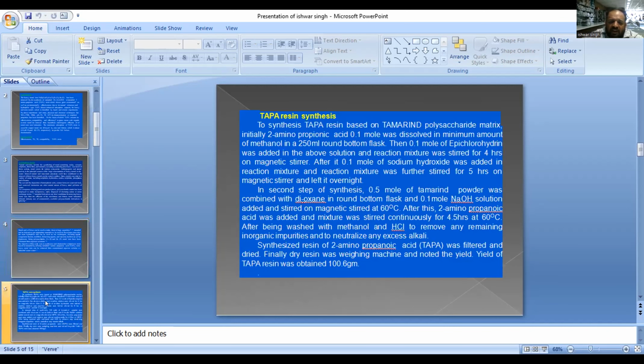Tapa resin is now how I start my work in the laboratory. First, I synthesize the tapa resin on the tamarind matrix. Initially, 2-aminopropanoic acid, which we also call DL-alanine, I have taken 0.1 mole and dissolved it in the minimum amount of methanol to remove all the impurities present. That is removed with the methanol.